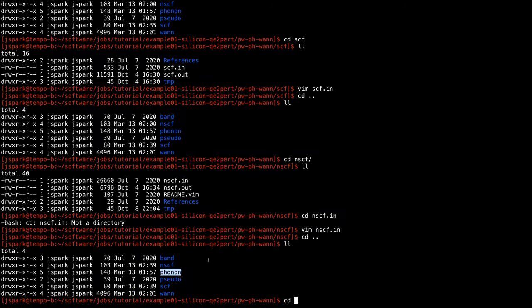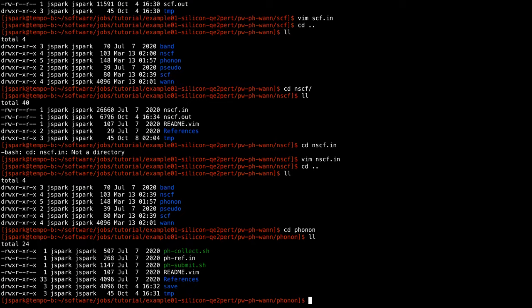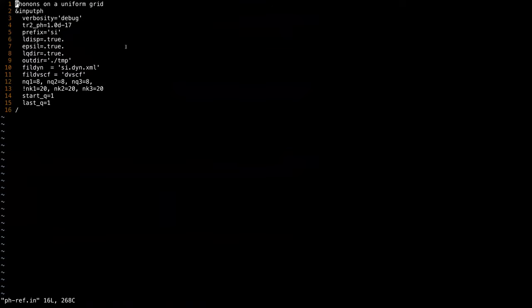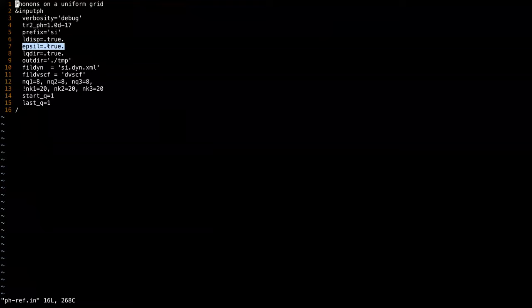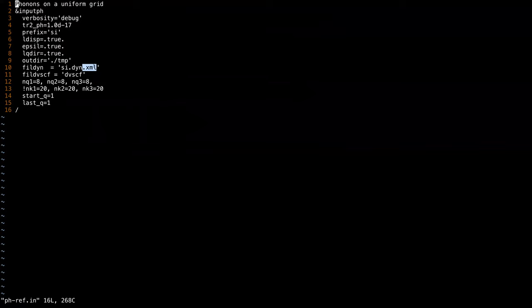Next is the phonon folder. Let's look at the phonon input file. There are many flags but I'll point out the important ones. The first is epsilon — if this is set to true, the code will compute the dielectric constant. You must set this to true if you are computing polar materials; however it does not have to be turned on for non-polar materials. The output directory is set to temp, and for the dynamical matrix you have to set the last one to .xml because Perturbo only supports .xml formats.